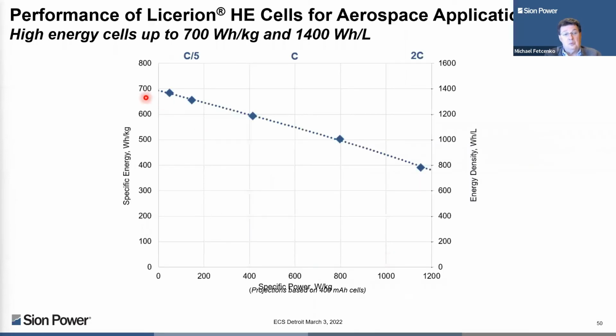So we've actually demonstrated aerospace designs where cycle life is not really so important. We've got test results at 700 watt-hour per kilogram and 1400 watt-hours per liter. Now, 2 things. We don't get the power that we need in that design for EVs for high rate charge and discharge, but that's clear from the graph that I'm showing you. We'll also sacrifice cycle life when we go to that 700 watt-hour per kilogram design. But for rockets, drones, high altitude communication, cycle life isn't so critical.